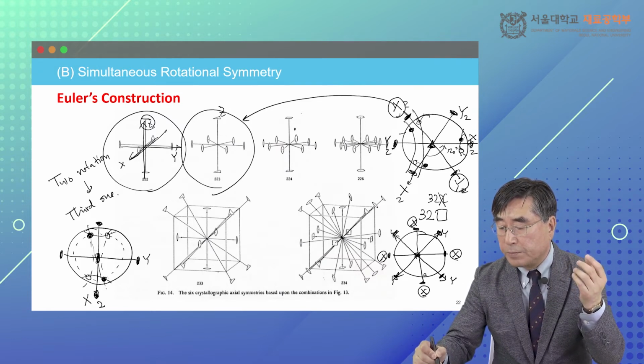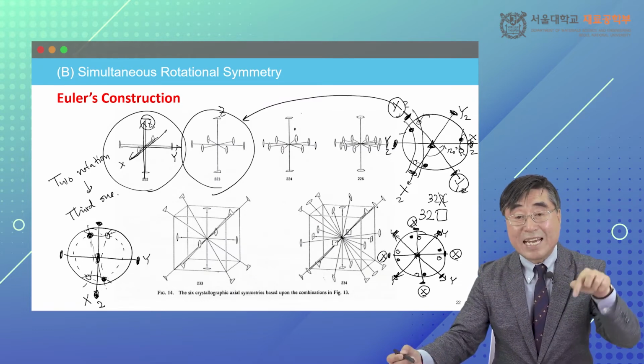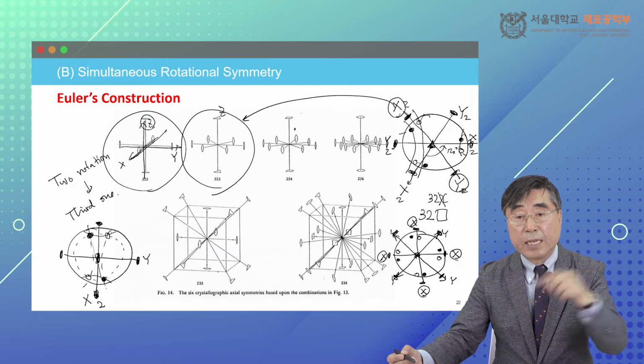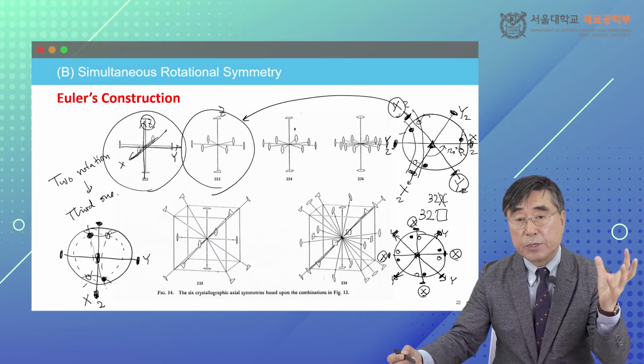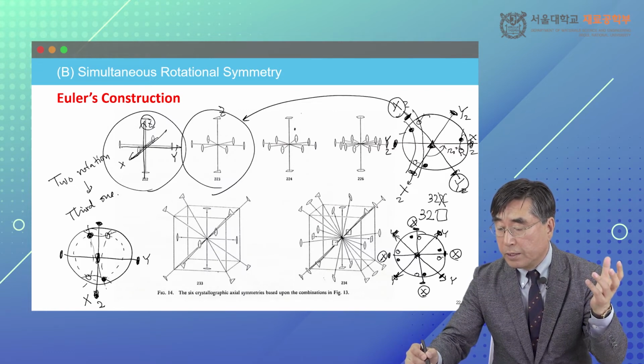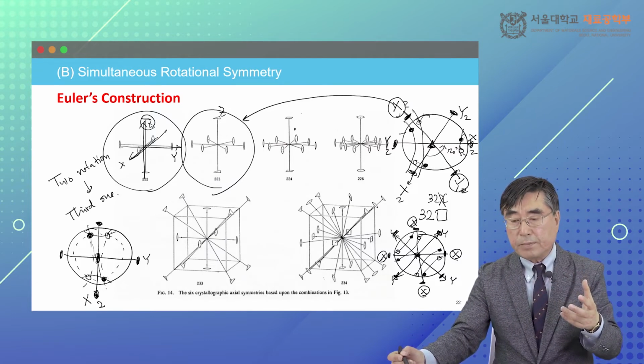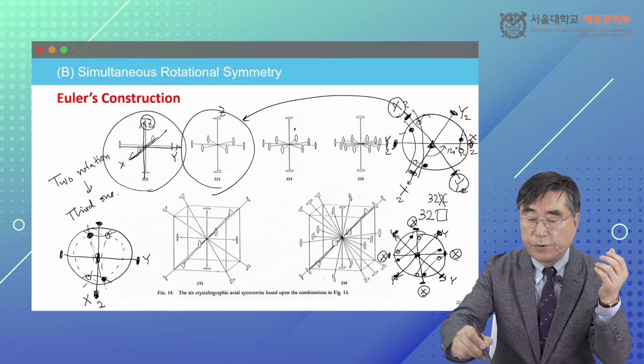Now if I put any poles in here, then 4-fold is generated in here. Now 2-fold generates here. I only do the 2-fold over x-axis operation. I didn't do any y-axis operation again. But you know that this y-axis again has 2-fold rotational symmetry, so it automatically matches. Okay, so this is 2, 2, 4.